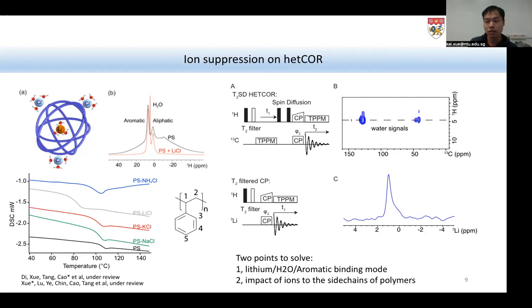So to prove that, we need to prove that water is close to the polymer, and we also need to prove that water is close to the ion. In order to prove that water is close to the polymer, we use this heteronuclear correlation experiment. But we started this experiment with the T2 filter. We can see from this spectrum here, proton signals from the polystyrene are actually much broader than the water peak. So water definitely has a much longer T2. We want our initial signal to completely come from water, and through spin diffusion and CP transfer, we can have the signals from water and correlate them with carbon sites on the polystyrene.